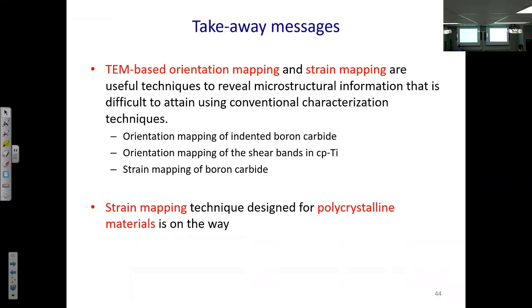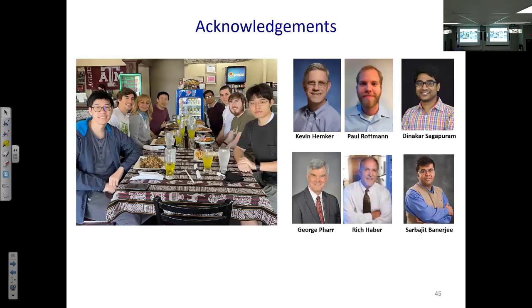Two main takeaway messages: first, TEM-based orientation mapping using PED provides much higher spatial resolution than EBSD and can reveal features well below the EBSD resolution limit, with potential applications in materials science, nanoparticles, nanowires, and possibly soil minerals. Second, TEM-based strain mapping can capture and quantify elastic residual strain at nanometer resolution with sensitivity of ~0.05%. Most of the work was done by group members, and I look forward to collaboration opportunities. Thank you very much for your attention.